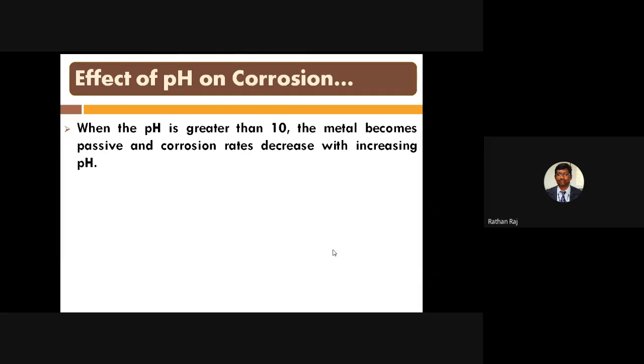Now, particularly when we talk about the effect of pH on corrosion, the concrete always has a pH value higher than 10. So the metal becomes passive, and the corrosion rate decreases with increasing pH value. Normally when concrete is used, the pH value is nearly 11 to 13.5. Approximately, the average value is taken as 12.5.